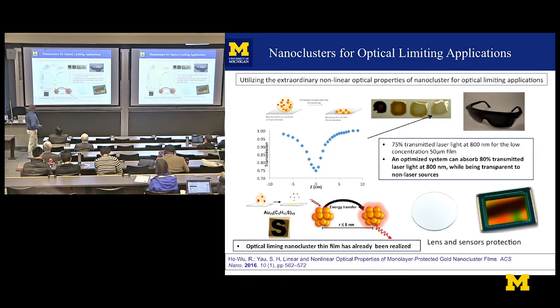And so this is still a goal. You would not like to have dark sunglasses when you're reading your normal paper, right? So she was able to make a material that was semi-transparent and had these enormous optical limiting properties. And look at the different types of properties that you can see based on the separation between these clusters. If you can actually control the separation based on the concentration, aggregation effects, and surface topology, then you can have materials that look transparent but still have these enormous optical limiting properties.